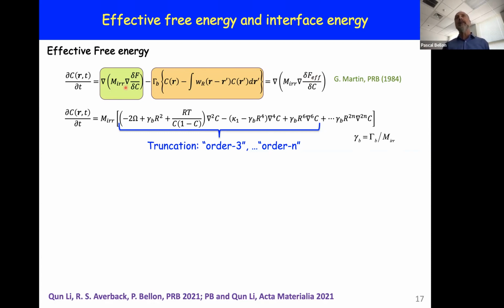So in the recent papers that are listed at the bottom of this slide, what we have done is that we show that you can perform, so to speak, a Taylor expansion of this ballistic mixing term in orange. There's a somewhat nasty convolution integral that becomes a series of differential terms for the composition field. And what's intriguing is that if you linearize the Cahn-Hilliard equation, you get a similar series of terms, at least the first two terms. So for instance, the leading term here is a Laplacian, so it's Fick's law. And there is a thermal part, but there's also a ballistic part, which is proportional to this driving coefficient gamma. The next term is one where normally we would have this gradient energy coefficient kappa 1, but here we see there's a term coming from irradiation, and there are other terms as well.